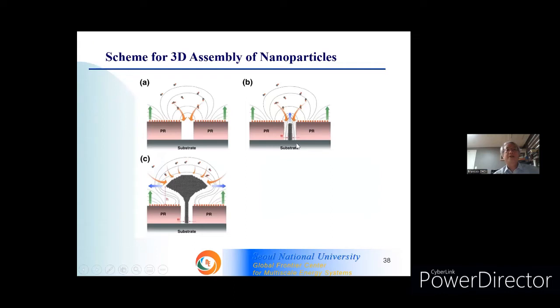The next task was to develop the technique for 3D assembly of nanoparticles. So we used the same technique here. Initially, particles deposit only at the center surface area, but prolonged deposition will grow particles upward, maintaining width. But after this structure grows beyond the PR height, it interacts with other structures, growing both vertically and laterally.